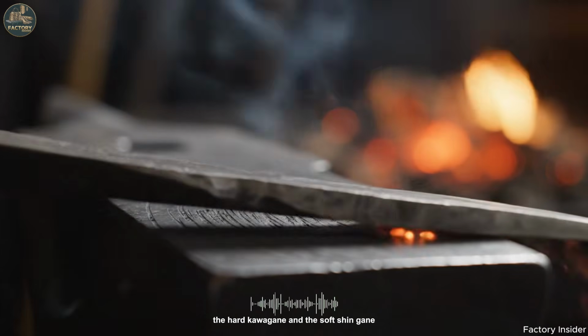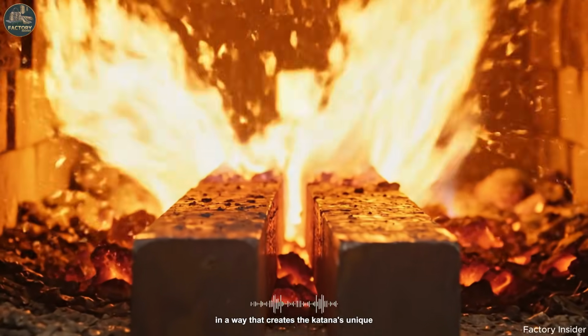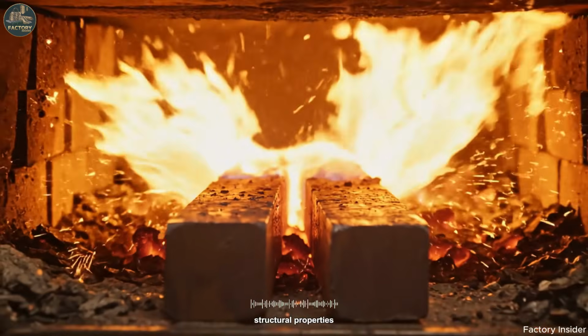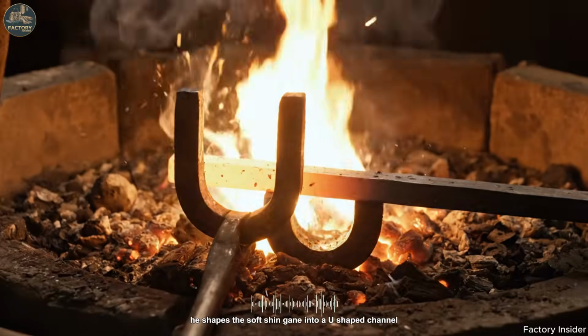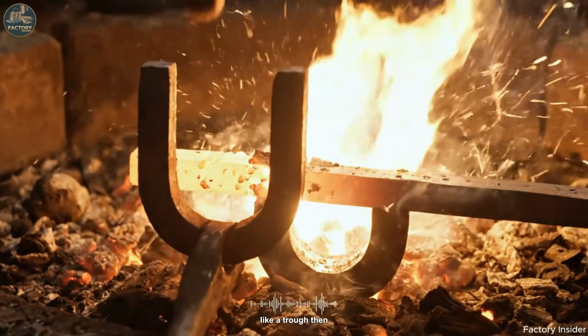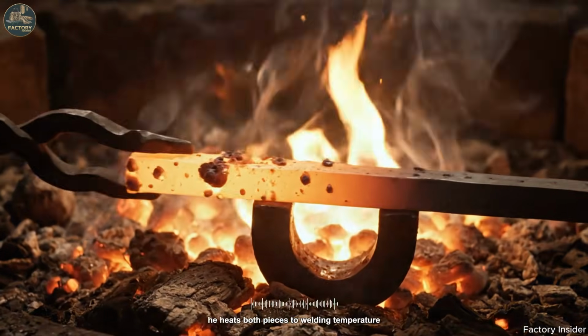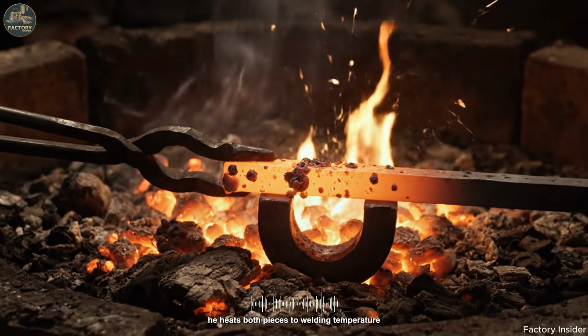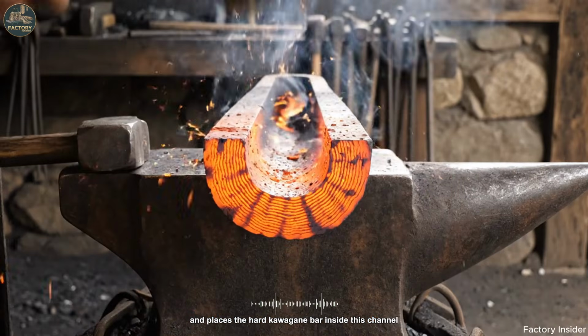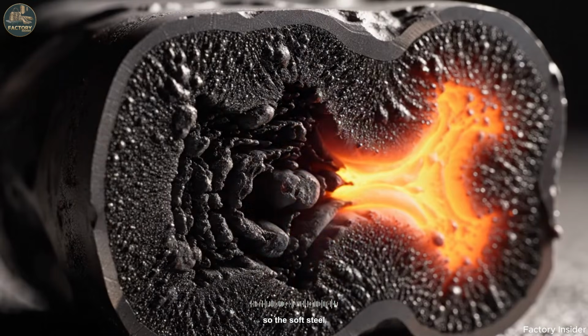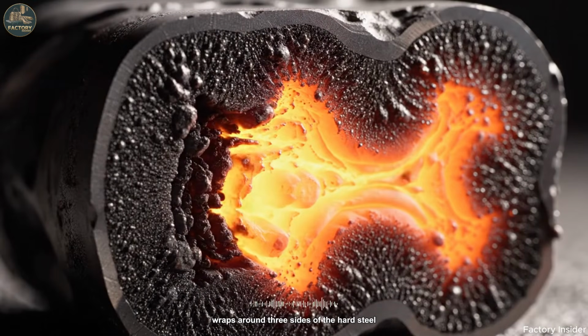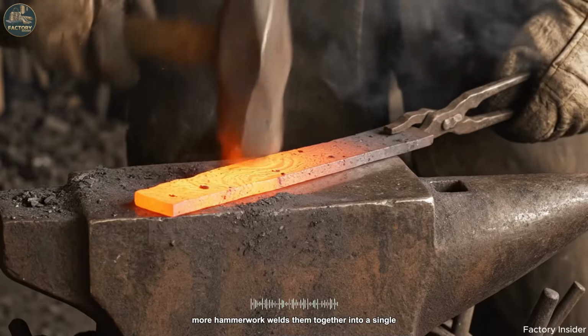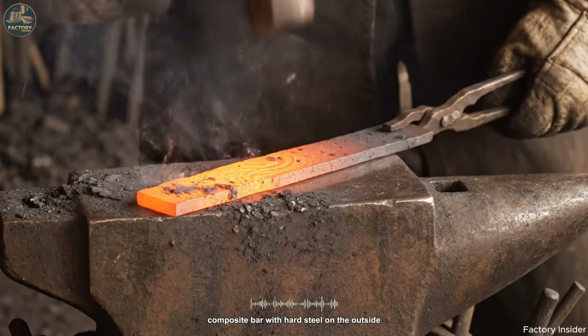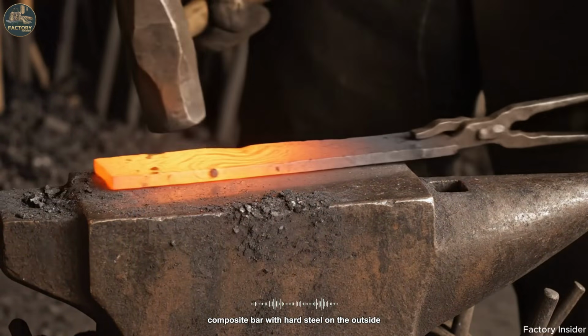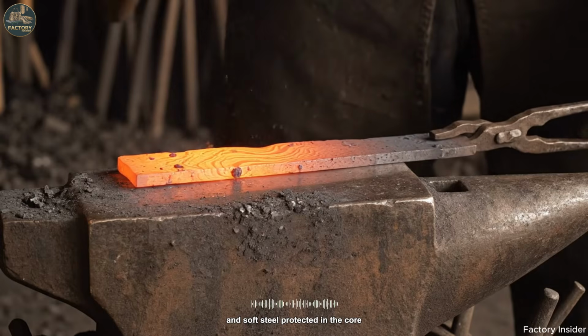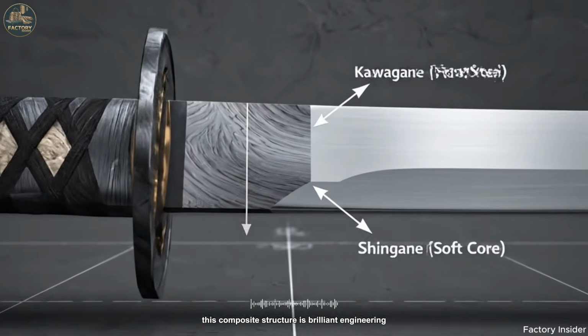After 2 days of folding, the swordsmith has 2 separate bars of layered steel, the hard kawagane and the soft shingane. Now he has to combine them in a way that creates the katana's unique structural properties. He shapes the soft shingane into a U-shaped channel, like a trough. Then, he heats both pieces to welding temperature and places the hard kawagane bar inside this channel. So the soft steel wraps around 3 sides of the hard steel. More hammerwork welds them together into a single composite bar with hard steel on the outside and soft steel protected in the core. This composite structure is brilliant engineering.